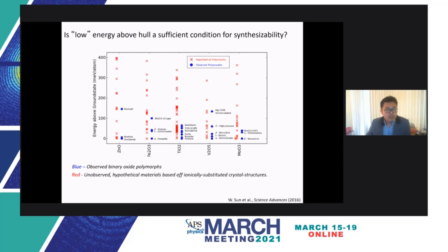Okay, so what does this tell us? There are 2 possibilities here. The first possibility is that there are still more TiO2 polymorphs waiting to be synthesized. There are about 40,000 papers on TiO2, so TiO2 has been synthesized so many times in nature and in the laboratory. We found it to be a little bit unlikely that there are so many TiO2 polymorphs still awaiting experimental discovery. Therefore we took the second option, which is that not all predicted low energy metastable phases may be synthesizable. And like Baden said earlier, there are probably energy basin arguments for this as well.